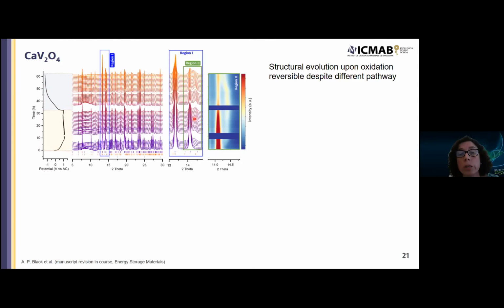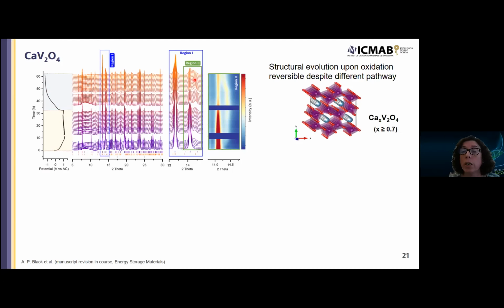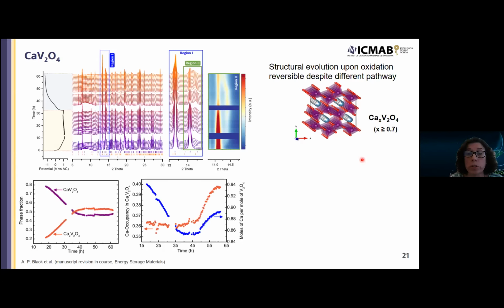So we seem to have a two-phase process here, and here we seem to have the formation of a solid solution. And this oxidized phase was found to have a stoichiometry of calcium 0.72, V2O4. So it's really not that much that we have been able to extract, and we're already at a very high voltage versus calcium.